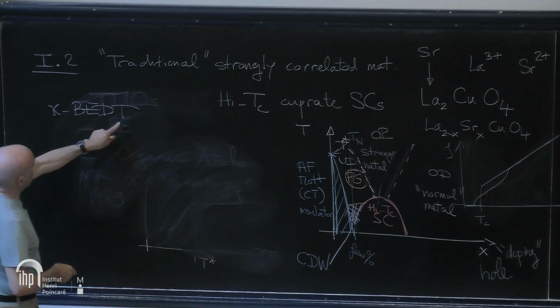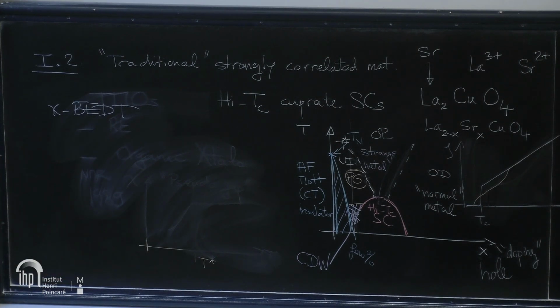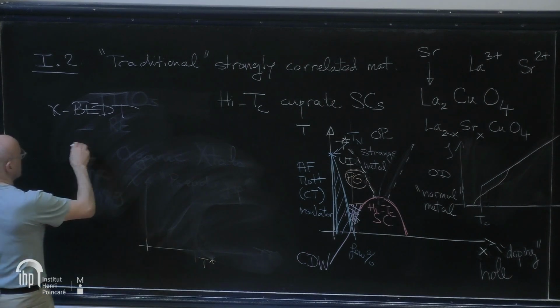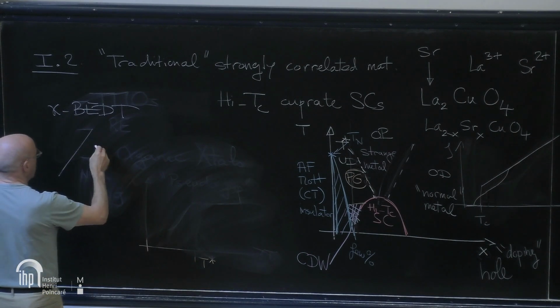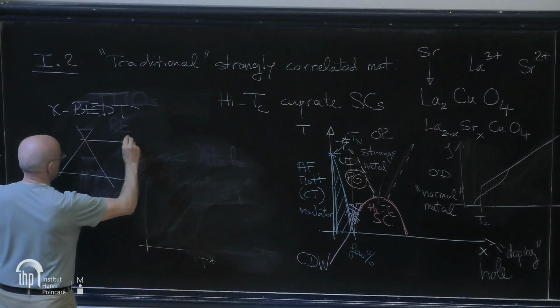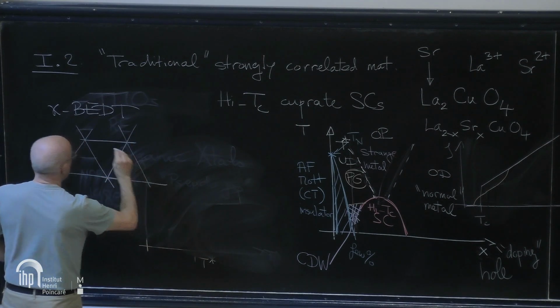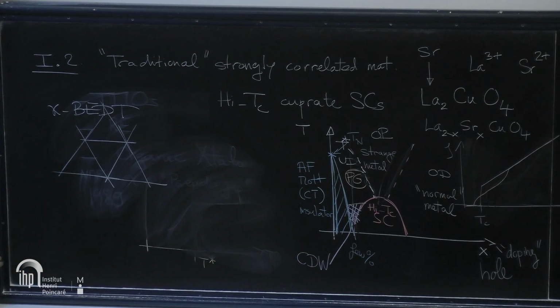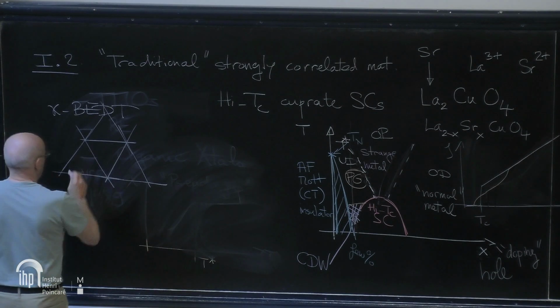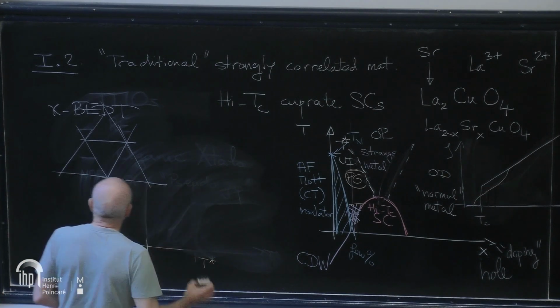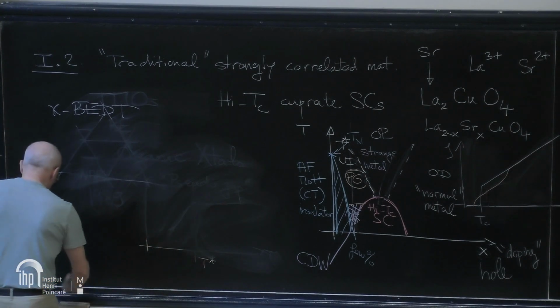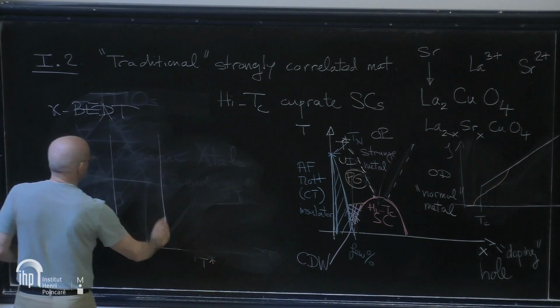And typically, in those systems, which are called the BEDT salts, these crystals form also planes, and these planes are actually triangular. So something like this. And these materials, perhaps in contrast to the cuprates, are very well described by a two-dimensional Hubbard model on the triangular lattice. Or more precisely, to be really accurate, they are anisotropic triangular lattices.